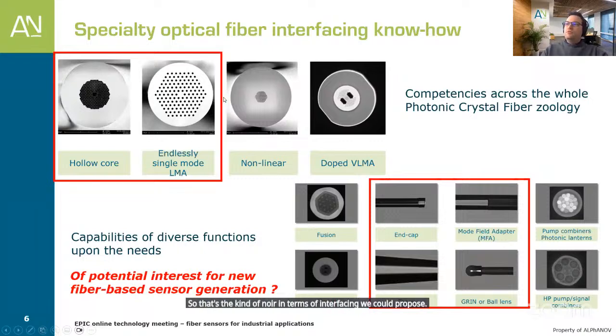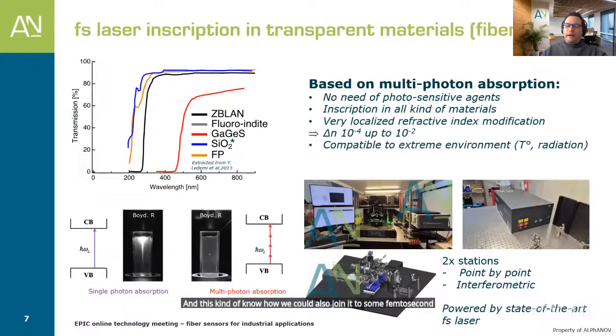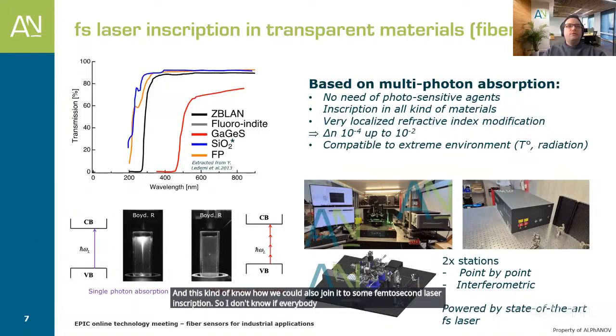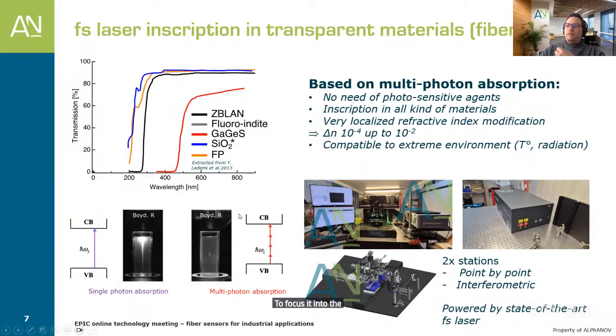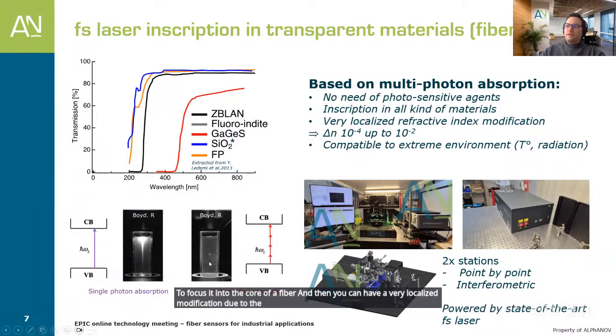And this kind of know-how, we could also join it to some femtosecond laser inscription. So I don't know if everybody in the room is very familiar with that, but the idea with femtosecond laser inscription is to take benefit of the fact that you are using a femtosecond laser, which has a very high peak power, to focus it into the core of a fiber. And then you can have a very localized modification due to the nonlinear effect, the multi-photon absorption effect, which is illustrated in this picture compared with linear absorption in the UV. And so you can have really very precise modification in the core of the fiber.